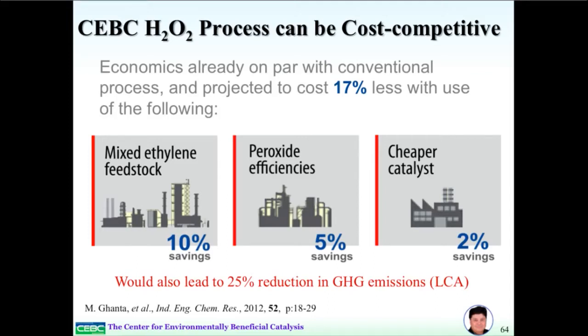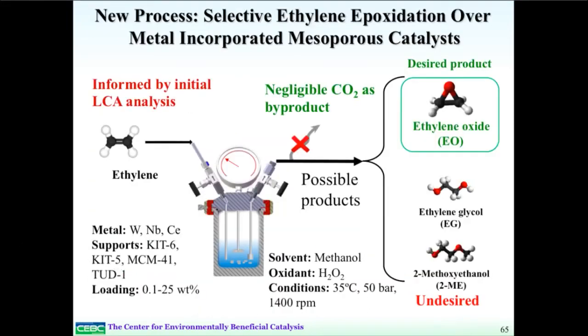for this particular process. So our new process is a heterogeneous catalysis method in which we use the same ethylene expanded methanol, except we have mesoporous silica, metal doped mesoporous silica as the catalyst. So here we have a variety of different types of mesoporous silica as the supports. This also gives negligible CO2 as a byproduct. There are a number of possible products. The selectivity is extremely high towards ethylene oxide. We're trying to optimize that.